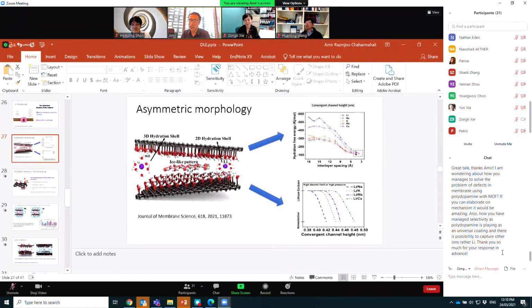The other question that you made is about polydopamine, PDA. Yes, you're right that polydopamine is a universal coating, but we use polydopamine to initiate nucleation and growth of the MOF thin film. So basically, we use polydopamine as an interlayer to support it, and we have a thin film of MOF on the polydopamine. So polydopamine wouldn't be in direct contact with the solution. And even if somehow any impurities manage to go through our MOF thin film, it's good because, as you said, polydopamine has a sort of reducibility. It traps the ions and reduces them.